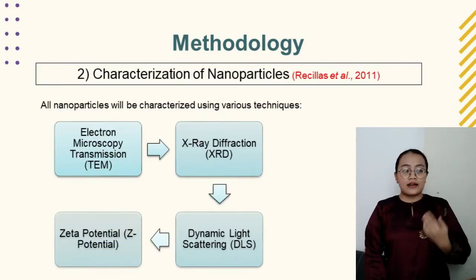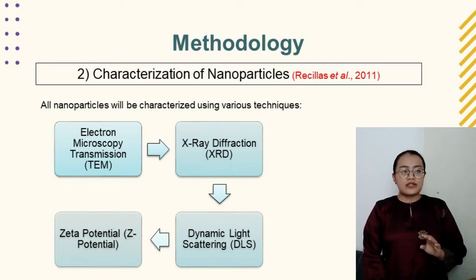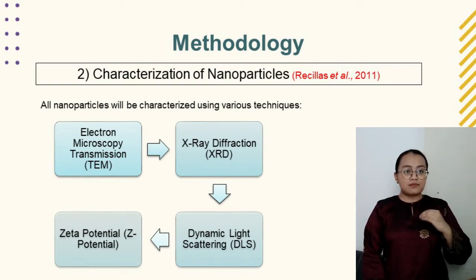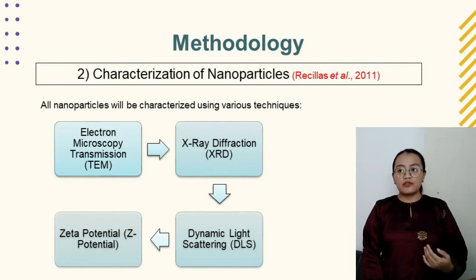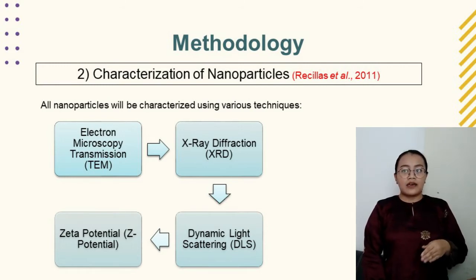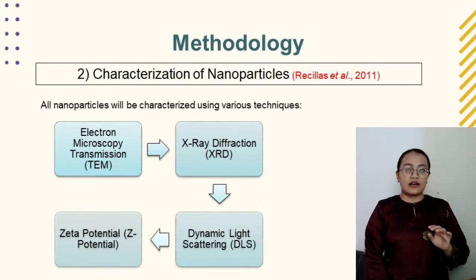Next is the characterization of the nanoparticles, which is taken from Recillas et al., 2011. In this process, all nanoparticles will be characterized using various techniques: transmission electron microscopy (TEM), X-ray diffraction (XRD), dynamic light scattering (DLS), and lastly zeta potential. At the end of the studies, nanoparticles will be removed from the colloid by centrifugation, and the pellet powder nanoparticles will be retrieved and dried.